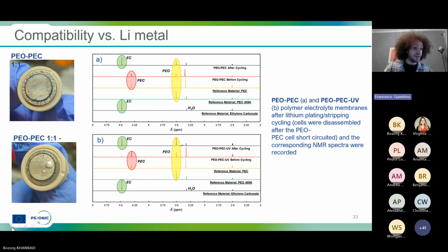In case of PEO-PEC-UV, instead, the membrane after cycling was still solid, and from NMR, we revealed that after cycling there is still the appearance of the ethylene carbonate peak, but in this case, the cross-linked network can retain this monomer produced, and it can act as a plasticizer, also improving the ionic conductivity. Next slide, please.